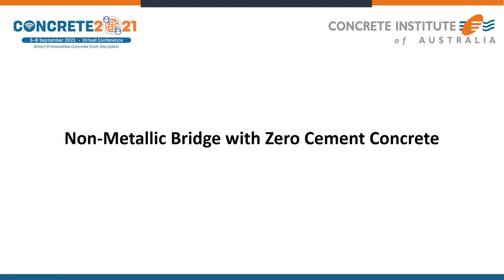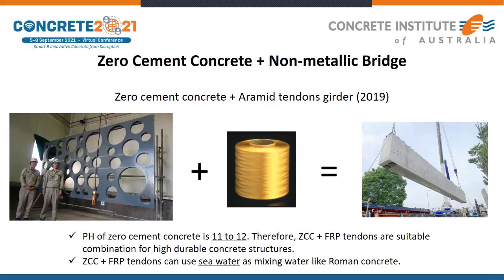Okay, the final example is non-metallic bridge with zero cement concrete. So we have zero cement concrete technologies combined with non-metallic technologies. Theoretically, this structure has no deterioration, and also the pH of zero cement concrete is around 11 to 12. So these technologies are suitable for the combination with plastic fibers, plastic tendons, which means highly durable concrete structures, because the zero cement concrete and FRP tendon can use, in the case of seawater as a mixing water, it is like a Roman concrete.